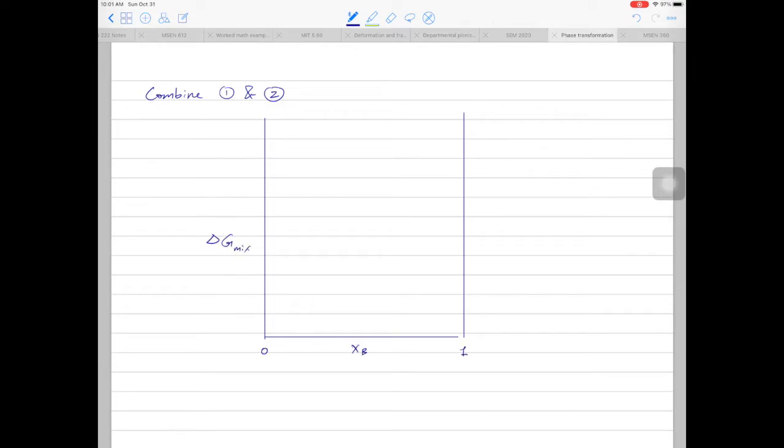Here we'll use the dashed line to show the rule of mixture. The solid line also accounts for the entropy. At a higher temperature, we'll use red color lines. The rule of mixture part does not change. The entropy does not change. What changes is the T. So G is equal to H minus ST. Then when T increases, Gibbs free energy also decreases.